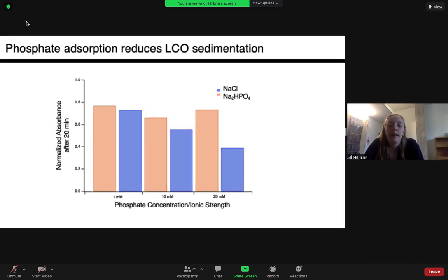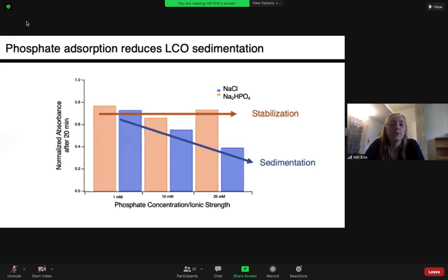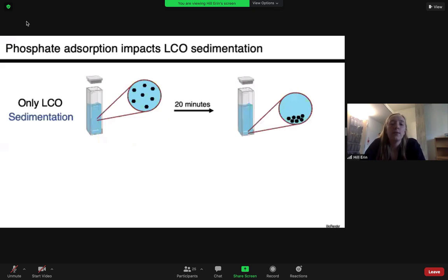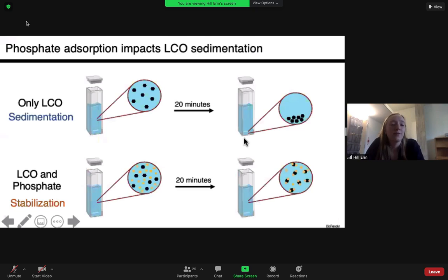This plot shows that with increasing phosphate concentration, we see a stabilization of the LCO in phosphate, whereas in the sodium chloride solution, there's a clear decrease in absorbance, indicating sedimentation. Our big takeaway from this is that LCO in the presence of phosphate remains in suspension longer than the control. With the ionic strength control, we only have LCO, and so we'd see this sedimentation at the bottom of the cuvette, whereas when LCO and phosphate interact, we see that stabilization when they bond, and so we don't see sedimentation.